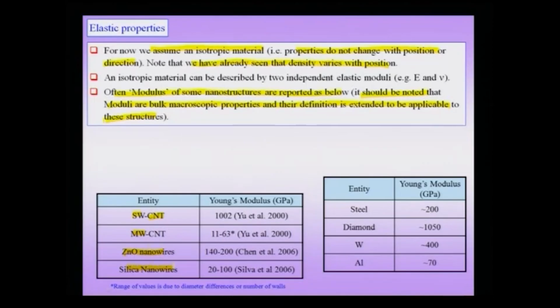Silica nanowires have been found to have modulus variation in the order of 20 to 100 GPa, zinc oxide nanowires from 140 to 200 GPa, multi-wall carbon nanotubes in the range of 11 to 63 GPa, and this obviously depends on the number of walls that the modulus is going to change. Single wall nanotubes have a very high modulus, which approaches that of diamond.